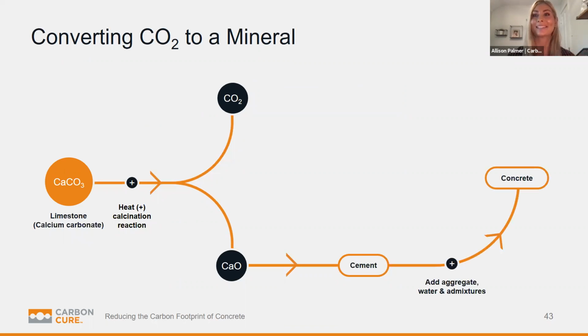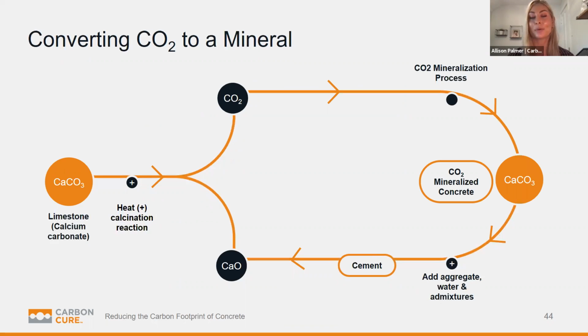Then cement is shipped off to our concrete partners that mix it with aggregates, water, admixtures, and other SCMs to form our concrete. And now this is where CarbonCure comes in. We deliver a precise dose of CO2 into the concrete mix during mixing, like I mentioned, just like any admixture. Once this happens, the CO2 enters the mix looking like dry ice or snow, warms up to room temperature, thus turning into a gas. Then it's like a magnetic attraction occurs between the CO2 and the calcium from the cement. These two molecules want to bind together and return to their original state of calcium carbonate, AKA limestone. So all we're doing at the end of the day is creating nano-sized limestone particles. These are the reactions that increase the overall strength of our mixes, which allows us to reduce that cement content, like I mentioned in the beginning.